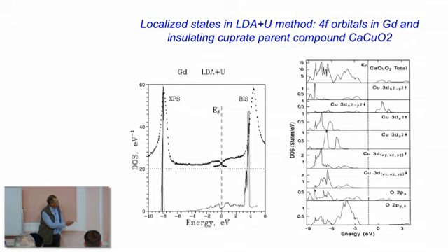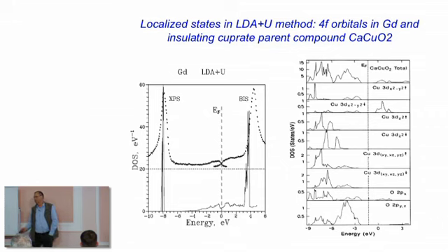And now something much more important. Transition metal oxides. As you see, now there are no narrow, sharp bands. Bands are relatively broad. Even D bands, you see, they are relatively broad. Nevertheless, the ratio of U, the Coulomb parameter, and the bandwidth is large enough to produce an insulator.